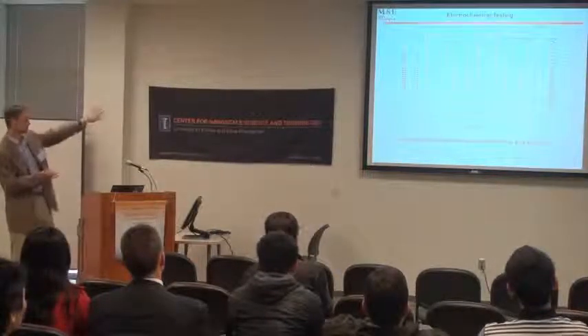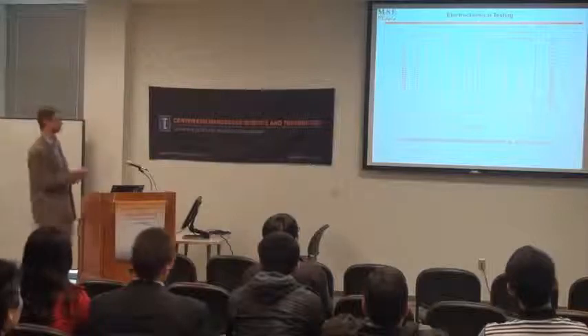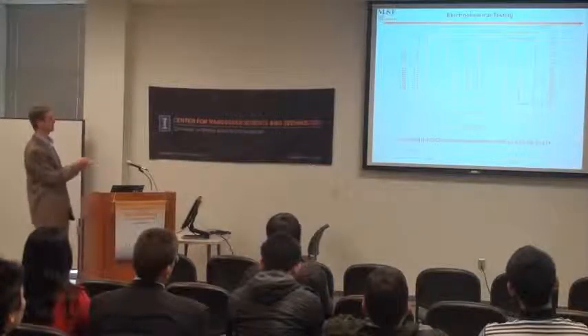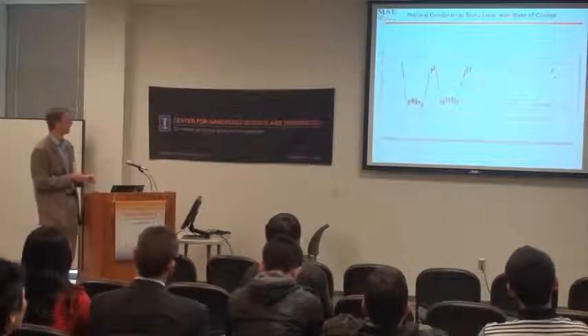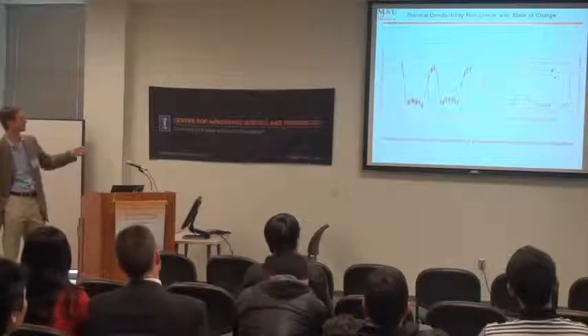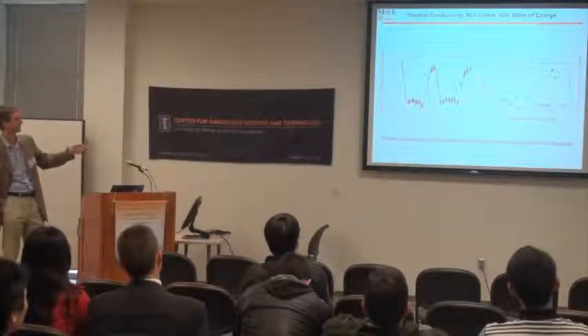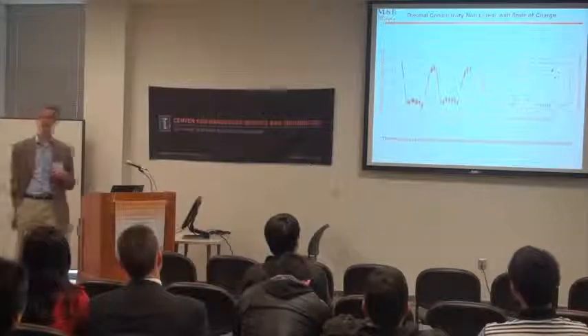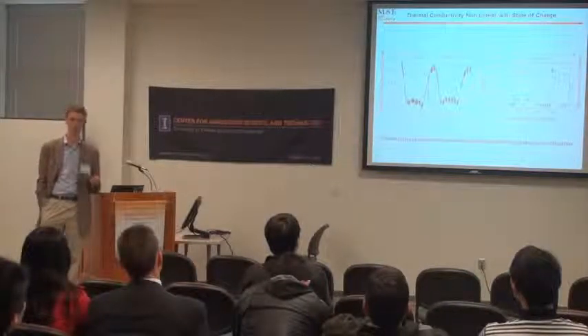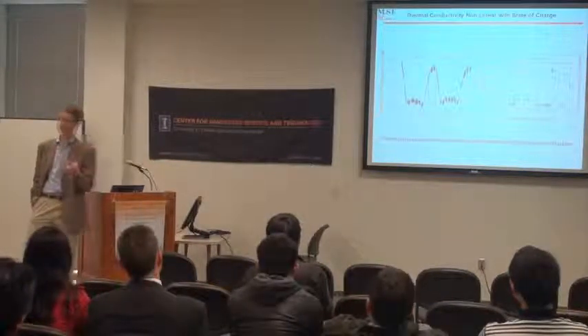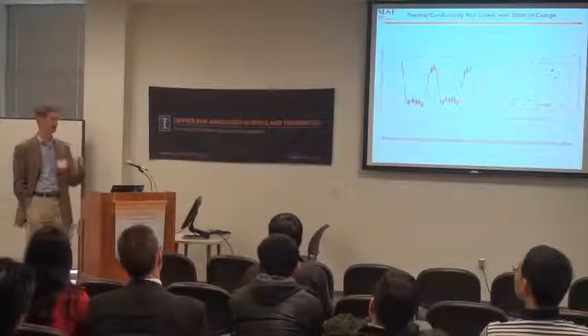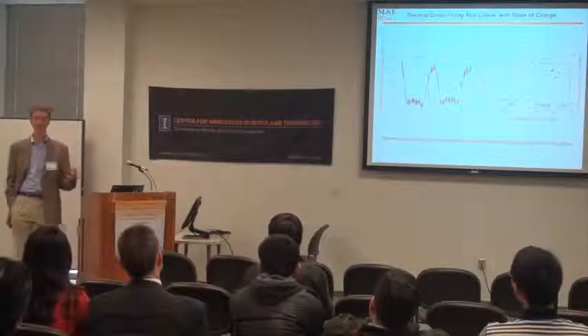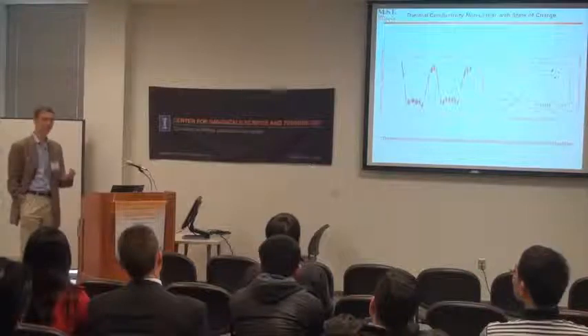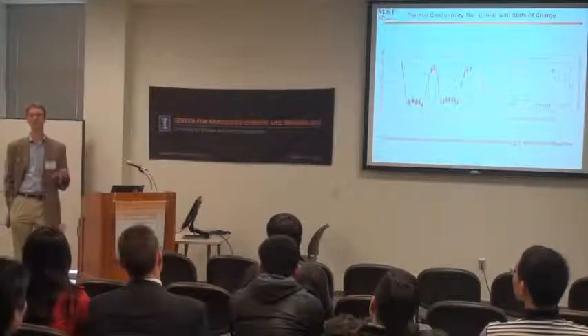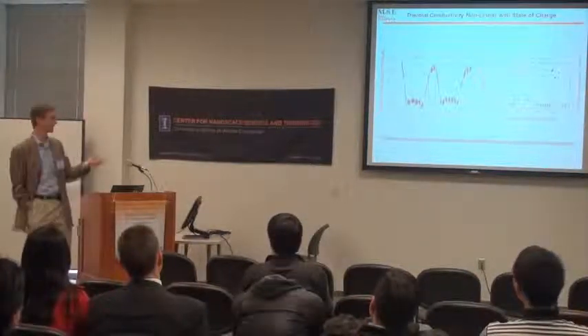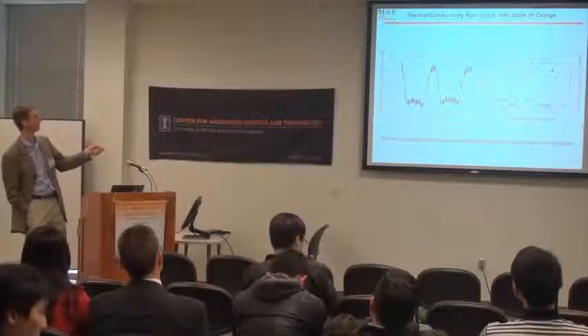And so we can still cycle the battery in a traditional fashion, and it follows what you'd expect in the current versus potential. But what's intriguing is that the thermal conductivity of this cathode varies by a factor of 2 between the charge and discharge state. And so as you start to charge and discharge batteries more rapidly, and you start to think about how do I get heat in and out of the battery, well, it turns out that the thermal properties of the constituent materials are not constant. They're evolving, and they're evolving actually in a nonlinear fashion.